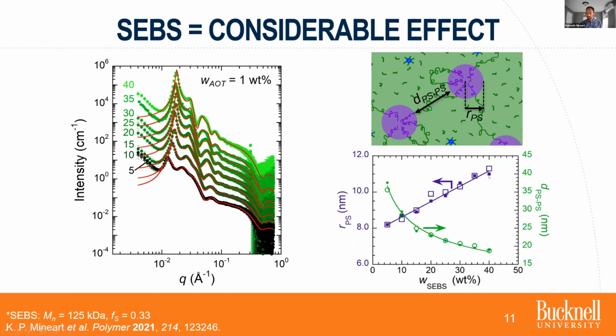And also what I'm showing here in open and closed symbols are the cases where AOT is present and not present. And so we basically see really good agreement, just like I talked about on the last slide, between 1 weight percent being in the gels and 0 weight percent being in the gels. So it really makes no difference there.